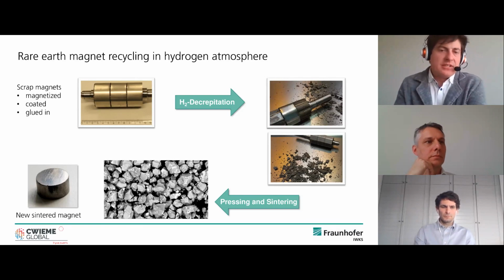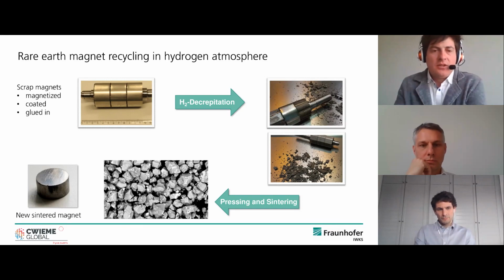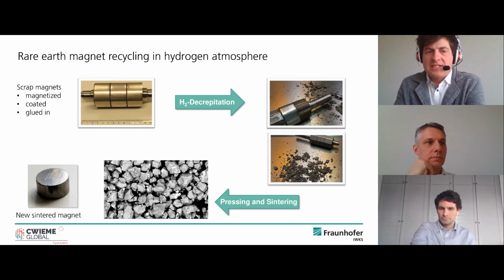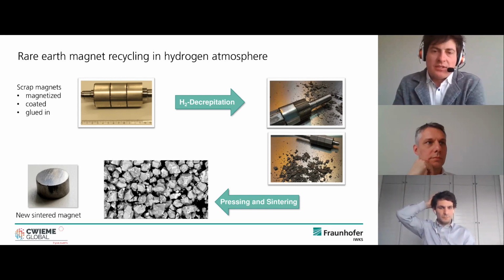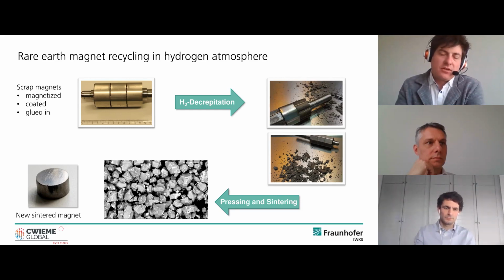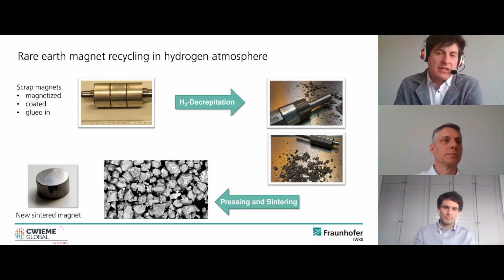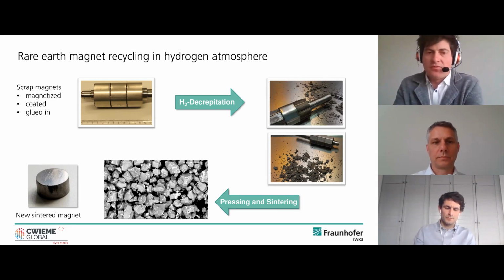In this case, we did it, for instance, with a rotor with surface mount magnets. You see it on the left-hand side. In this case, it was magnetized. It had some glue, but it was basically fixed with the steel plates, with the steel rings. And after hydrogen decrepitation, you can separate the powder from neodymium iron boron from your motor, because the hydrogen in these conditions just affects the magnet and not the steel part. So you have some powder, and this powder, like I showed you before, you can further process, and then you get a sintered magnet.